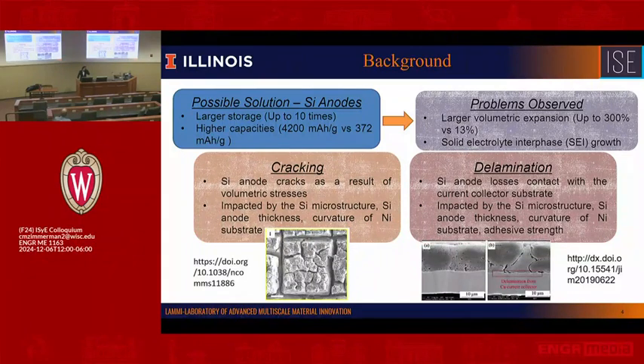Such a large volume change can lead to mechanical failure of the electrode. Two typical mechanical failure mechanisms we have been observing from experimental testing are cracking and delamination. So cracking and delamination are the two major failure mechanisms that have been observed for silicon-based anodes. A lot of techniques or methods have been explored to address such serious mechanical failure or degradation.